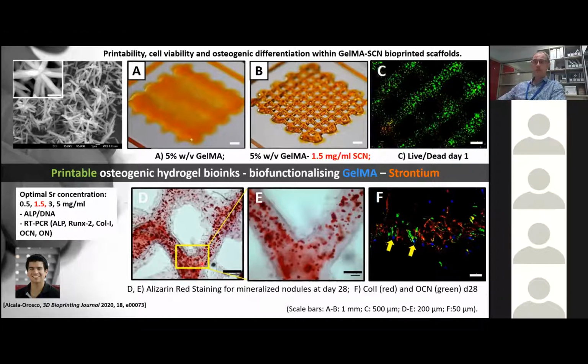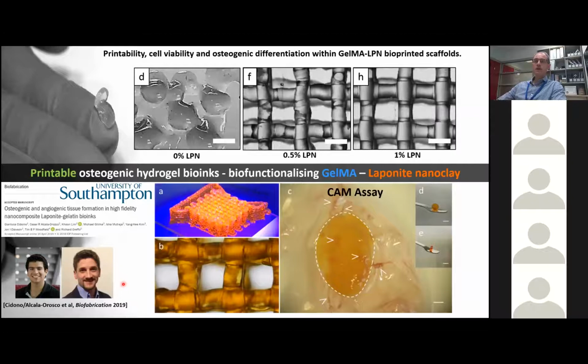Strontium, of course, is a potent osteogenic differentiation factor. So it was nice to see that we were able to print these constructs in the presence of mesenchymal stromal cells and culture them in the presence of osteogenic factors. We can get mineralization and nodule formation in these inks over time. So that was a dual function capability of using a strontium nanoparticle.